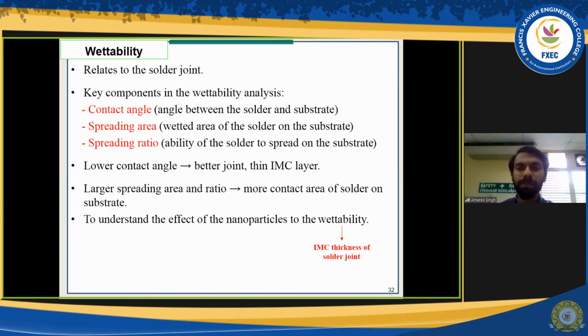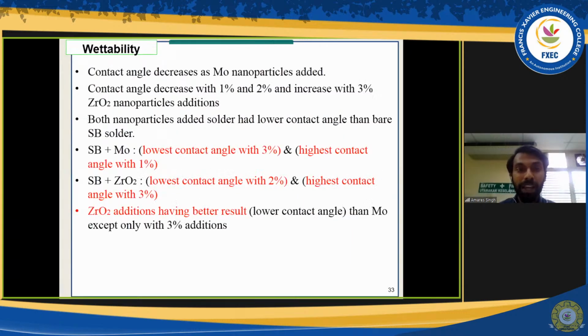So what happens when I test it in terms of wettability? A contact angle, as I mentioned earlier, is the angle between the solder and substrate. Spreading area is the wetted area, the area of the wetting or the soldering that took place. So we are going towards a lower contact angle, larger spreading area and larger spreading ratio. Upon my additions of nanoparticles, I have gathered a few data. We can see that upon additions of molybdenum, all three had a lower contact angle than the non-added, with the lowest for the 3%. For zirconia, we also found that the lowest contact angle is for the 2%, whereas in all other cases it is still lower than the SnBi solder alloy. So we can say that the nanoparticles here have reduced the contact angle and also increased the spreading area.